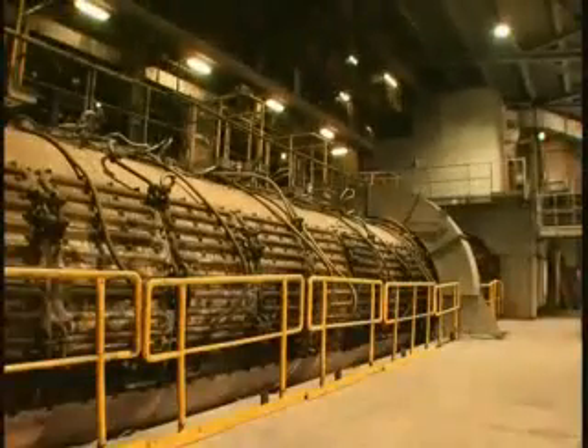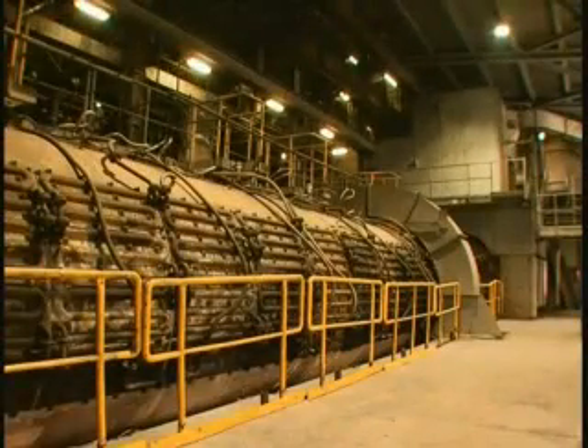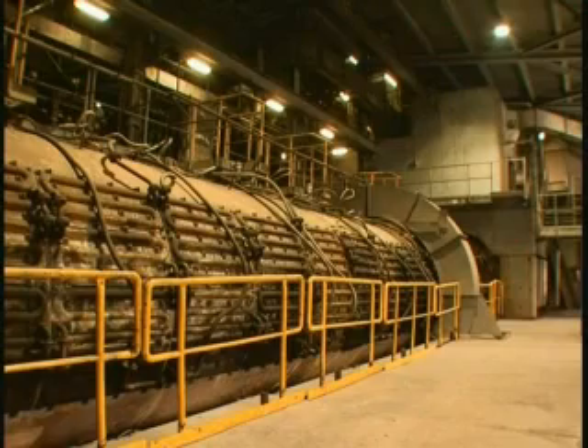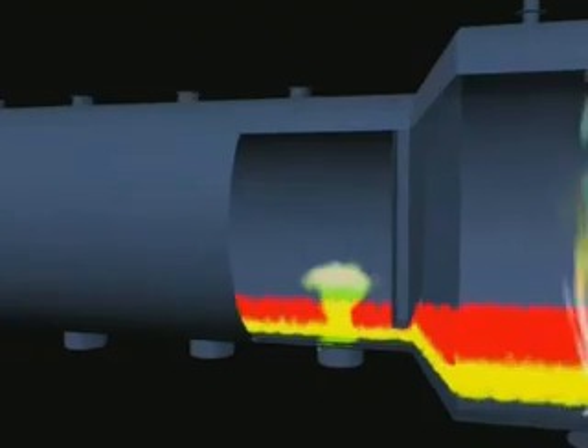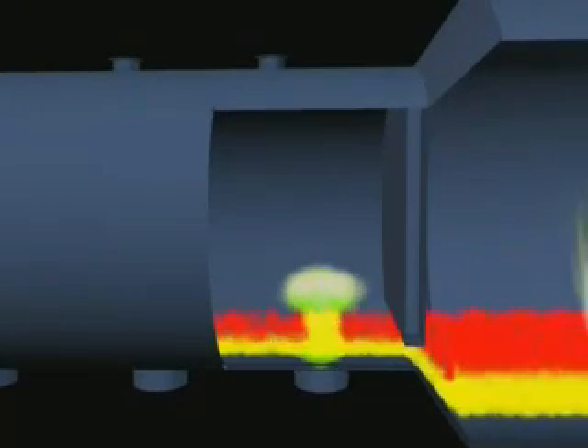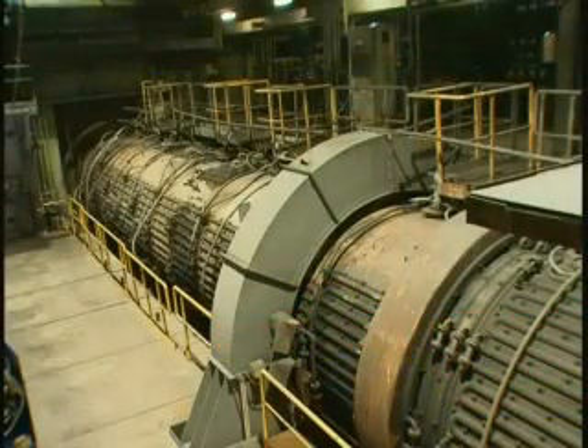In the second half of the reactor, a basically different process takes place. In this so-called reduction zone, the substantial amount of lead oxide still contained in the slag is reduced by injecting pulverized coal in a so-called carbothermal reduction process. The metallic lead thus obtained flows back to the oxidization zone.